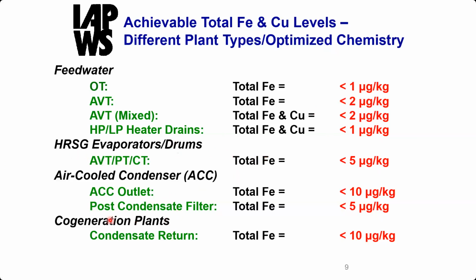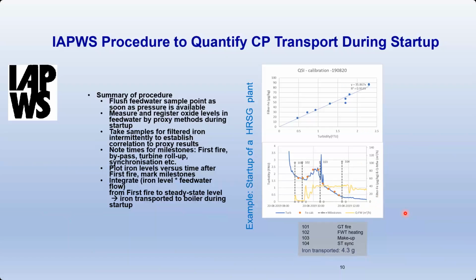And if you have an air-cooled condenser, the achievable level for iron, if you have a filter, usually we like a 5 micron absolute filter, we want it to be less than 5 micrograms. And so these are good guidance levels for you to aim for. And we know that if these are exceeded, the amount of deposits will actually increase. And go to the next slide.